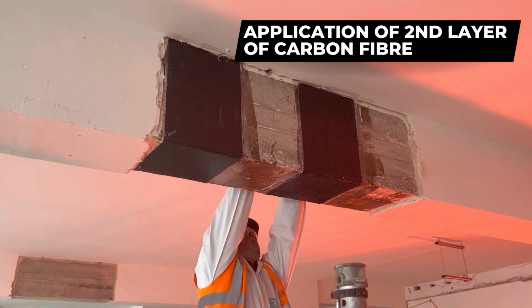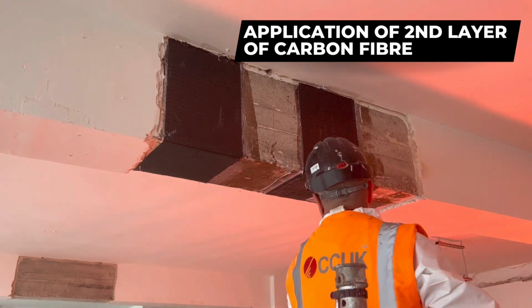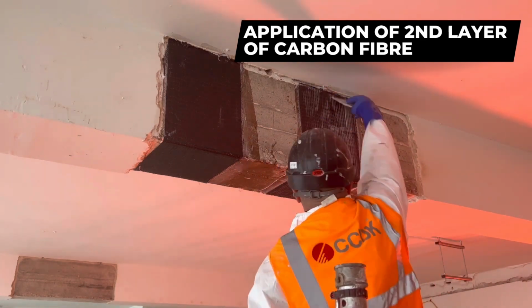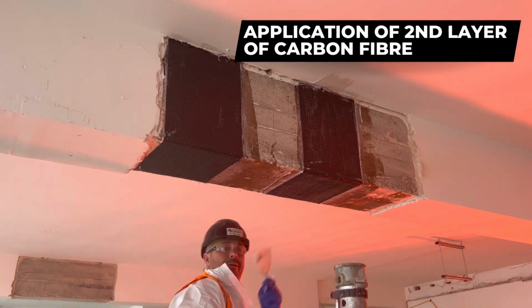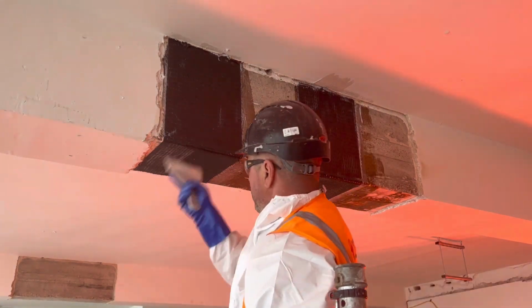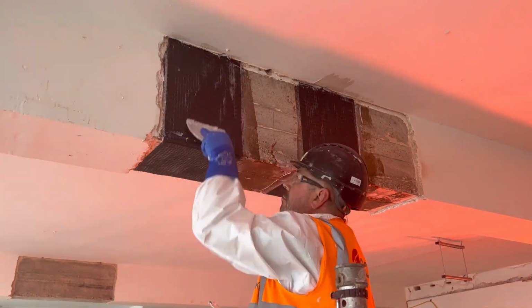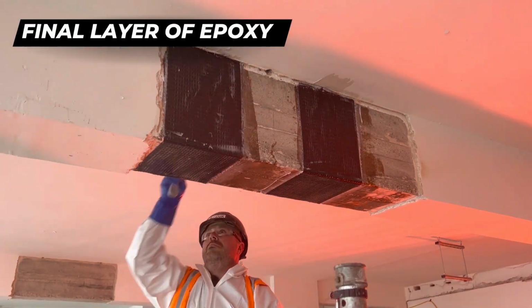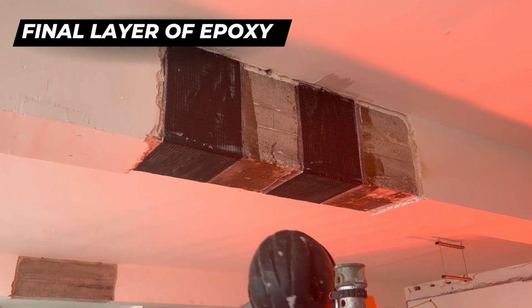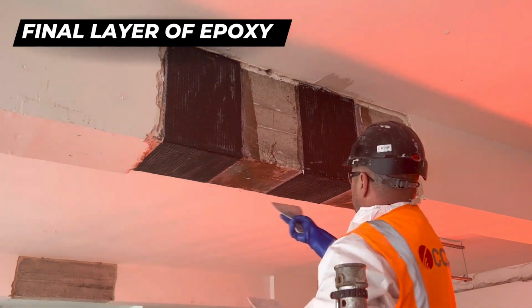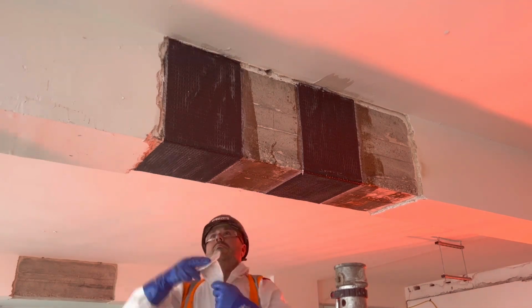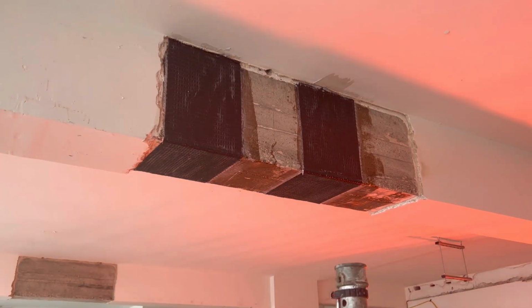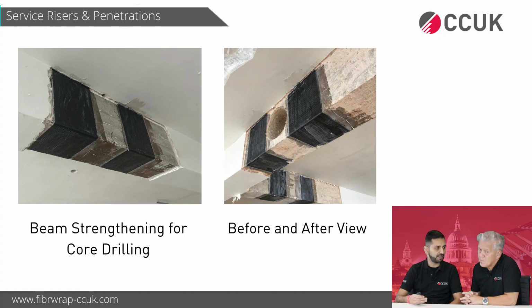So that's how we apply FRP. We apply the first coat, then this guy inserts the carbon fiber anchors, splays them, puts another coat of epoxy, then another layer of FRP, and that's how you build up the number of layers. Once you have applied the required number of layers, you'll have to let it cure. Generally in ambient conditions, it will be cured in 72 hours or 3 days, which means you can reload your structure back to its new capacity in 3 days. In this instance, they were able to cut the core through the beam in 3 days' time, which is the quickest way to strengthen any structure.